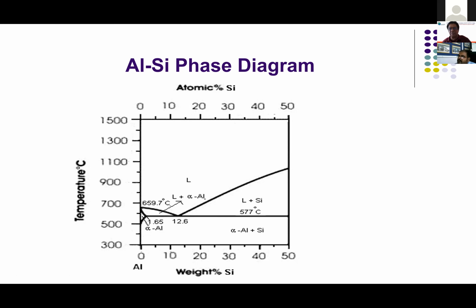You have to maintain a very high temperature. Beyond 810, 820, 830, your melting loss will go up. So the alloy maker tends to keep the temperature and silicon solution at a balanced level, so that he doesn't spend too much on fuel. At the same time, he ensures that the silicon goes into solution properly.